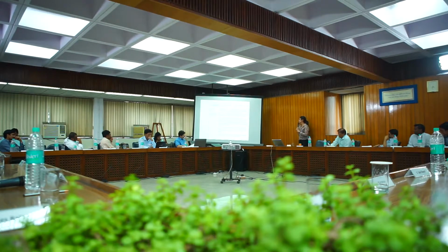Thallium, which is the semi-volatile, is the one I said has this recirculation and accumulation of thallium on the filter, on the upper stages of the preheaters and the filter. And then just a remark at the end: the removal of the dust from a kiln bypass will be less effective to remove thallium, of course, because it is there and not down, compared to the removal of cadmium and lead. So more or less this is how it shows the behavior of the volatiles in the clinker process.